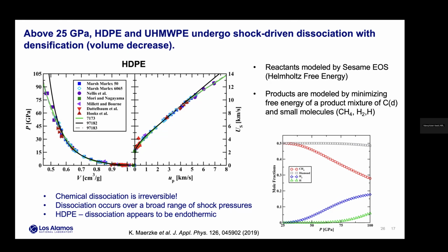Sure. Interesting. Yeah, so I'll just point out, we've probed above that cusp for both high density polyethylene and ultra high molecular weight polyethylene. And one of the new techniques that we did to do this was we performed some shock release experiments at very high pressure so we could get sound speed. But we have developed these new equations of state. So the historical equation of state is Sesame 7173.